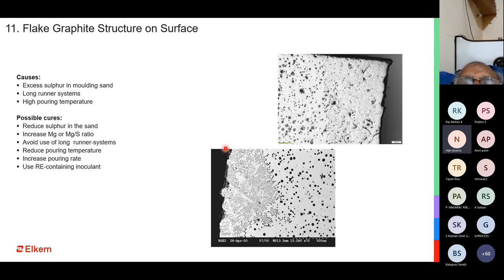So we have to combine our magnesium and sulfur to see how much is my base sulfur, how much is my final sulfur, and then how much magnesium do I actually need to make sure that I get graphites at the same time I do not get flakes. So that is why it is important to adjust and choose your final magnesium and final sulfur in such a manner that you get a good quality combination and good quality graphite nodules even on the surface.